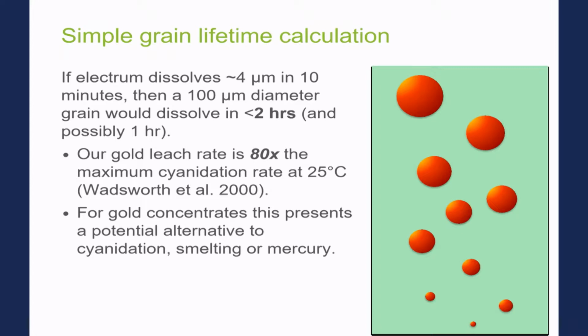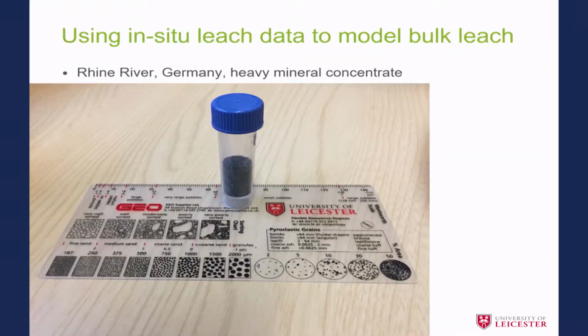Okay, so that leaching rate is about 80 times faster than the cyanidation rate. So what we've got here, just looking at gold, is a potential alternative to cyanidation, smelting, or mercury. Okay, so potentially much better process. So we've got these data on how fast material dissolves on the surface of a section, and we're using this to model bulk leach experiments that we're now running.